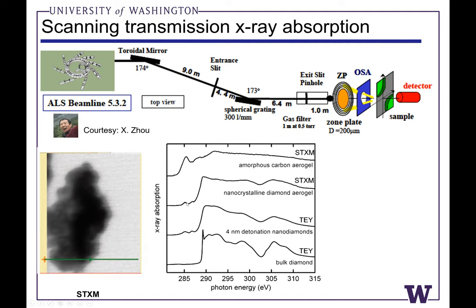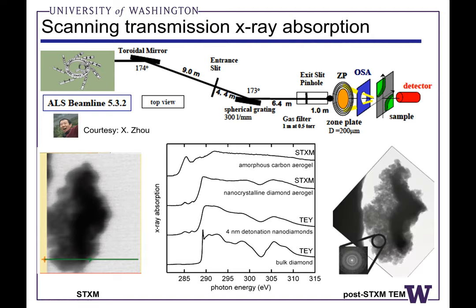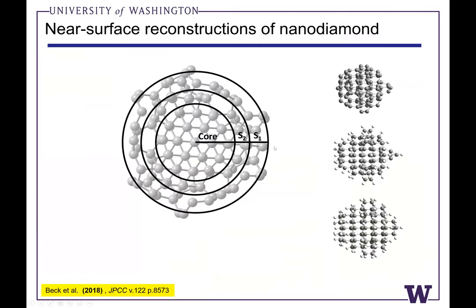We think that there's most likely a graphitic surface reconstruction around the surface of the diamonds. This is just some electron diffraction after X-ray absorption to show that we didn't completely obliterate the bonding and diamond crystal lattice during the X-ray absorption experiment. But that pre-edge feature at 284 electron volts, we think what's going on is a surface reconstruction. If you use neon, for instance, or argon, they're very noble gases. They don't form covalent bonds readily with any other elements in the periodic table normally. And so we think what's happening in terms of this pre-edge X-ray absorption feature is the carbon atoms on the surface of the diamond grains have nothing else to bond with, and they're effectively bonding with each other to make graphite or a sort of reconstructed graphitic-like phase at the surface of the diamonds.